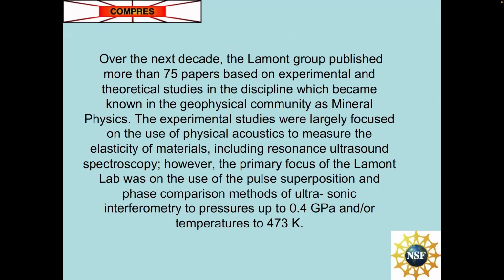Over the next decade, in the 60s primarily, the Lamont group published more than 75 papers, both experimental and theoretical, in mineral physics. Most of the experimental studies were focused on using physical acoustics, not only for resonance ultrasound, but primarily the techniques of pulse superposition and phase comparison to measure pressures up to what seemed to be a large pressure then, 0.4 GPa or 4 kilobars, and temperatures about 500 K. The next slide.